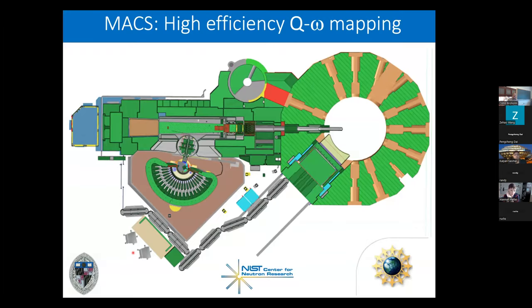But we're still using reactor facilities as well, both at Oak Ridge and also at the NIST Center for Neutron Research. Here's a picture of the NIST Center for Neutron Research reactor. It's a 20 megawatt reactor, and at this facility we've built, and Pingcheng mentioned this, the MACS instrument, which is an instrument that covers the whole plane of scattering more or less at once, and is very powerful for measuring low energy excitations in materials that have either a continuum of scattering or that have very slow quasi-particles. So it's tailored for the kind of research that we're doing, and we would love to be able to use it